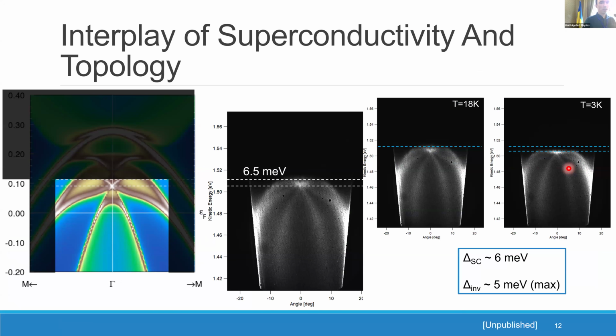But another important factor is superconductivity, and this is the analogy that I was talking to you about before. In this case, LiFeAs has a TC of 18 Kelvin, and its superconducting gap is around 6 meV. It was already reported in the literature. It also arose as the same number from our experiments. This is laser ARPES, because we wanted to have the highest resolution possible.